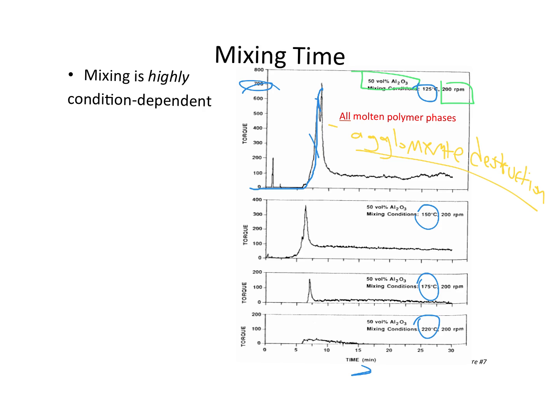Okay, so that's happening, and then after that, things kind of settle down because you've dispersed it, all right? You've gotten at least to, you know, maybe bad dispersion, good distribution, something like that, all right? So now the viscosity has dropped off. You've got your mixing achieved. You're kind of good to go, all right? But why does it change so much? If we go from 125 to 150, we go from 700 to maybe 350, and then 175, it's about 150. And then 220, it's not even that. It's whatever it is, 20 or 30, something like that. Why the big change? At least a couple of reasons here.